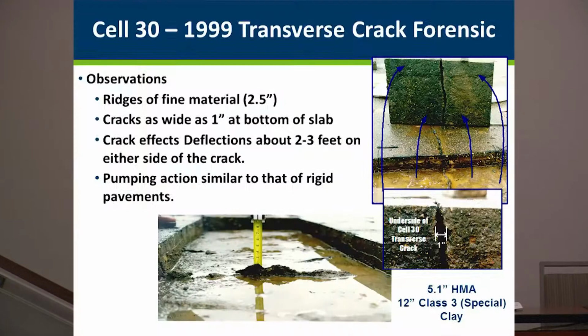Just showing that, you know, thermal cracks, when they do happen, this has nothing to do with polymer modified, but I think it's really interesting seeing how much water is underneath the pavement, how much the need for drainage is. I think that's one thing that we don't talk enough about, drainage and the need for drainage for pavement performance. But we get cupped cracks, transverse cracks that deteriorate, and that's one of the big problems in Minnesota, how to deal with those.